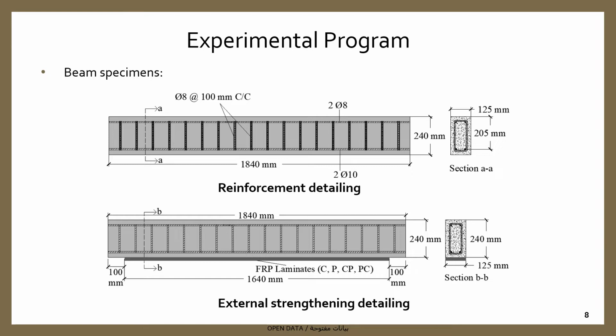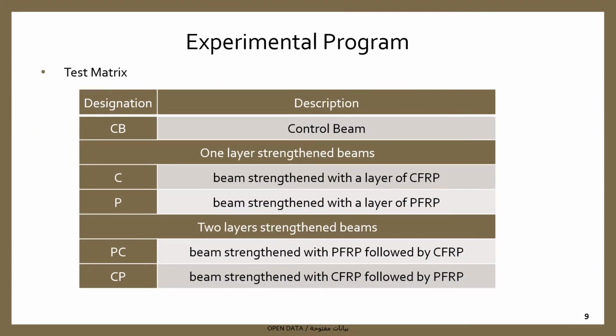Specimens were reinforced in flexure with 2 number 10 bars in the tension zone and 2 number 8 bars in the compression zone. In addition, they were reinforced in shear with number 8 stirrups spaced at 100 mm center to center. The flexure strengthening laminate had a total length of 1640 mm and a width of 125 mm. The beams test matrix of the study is shown in this table.